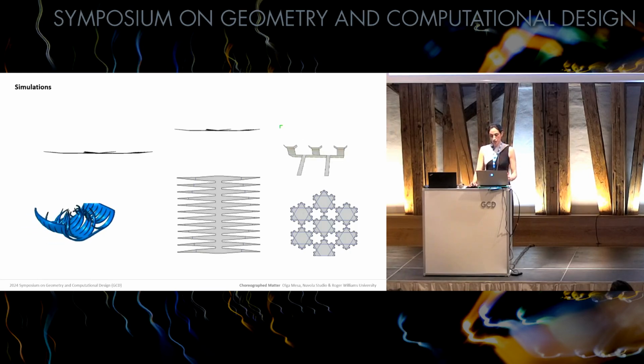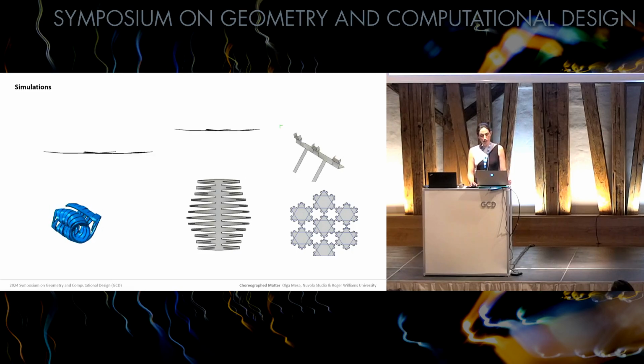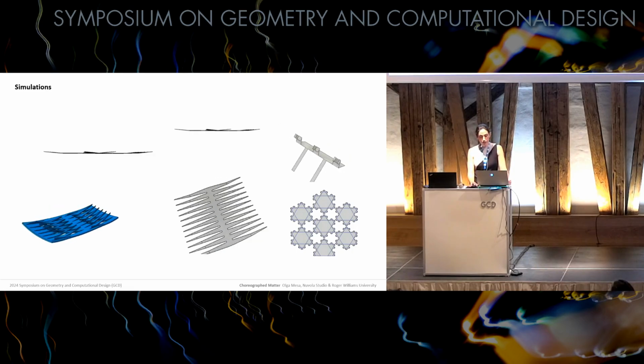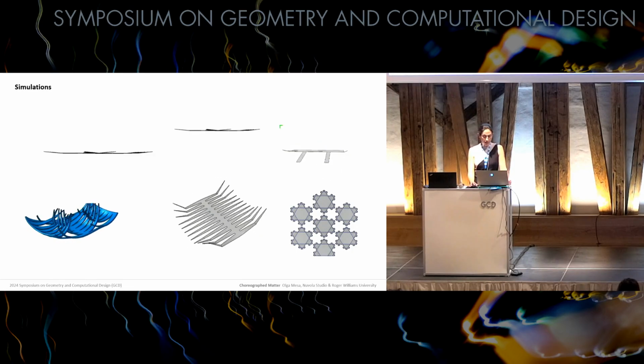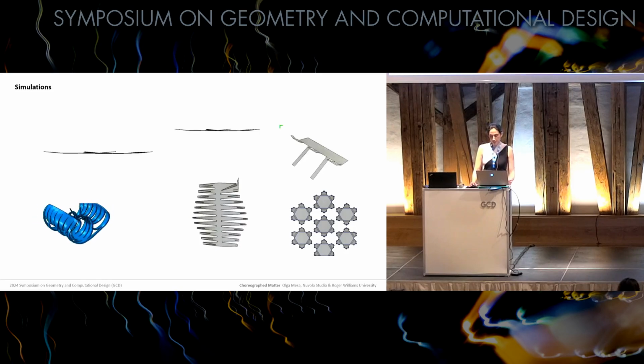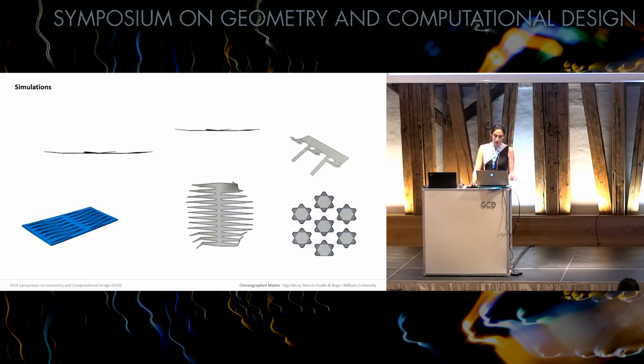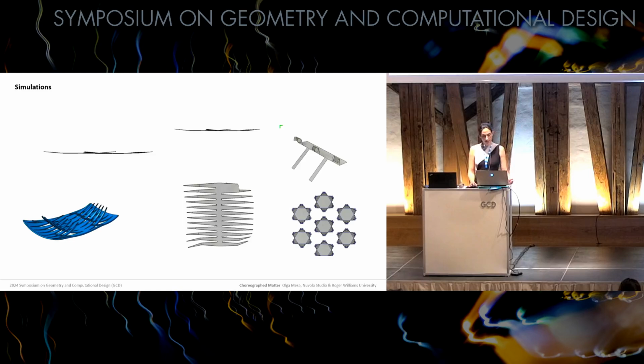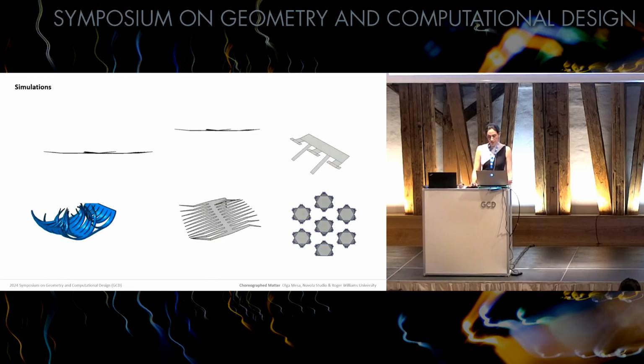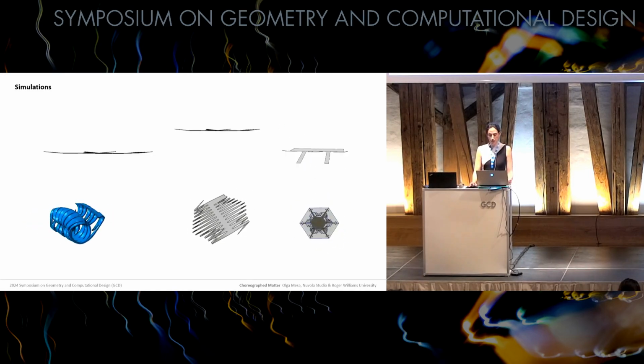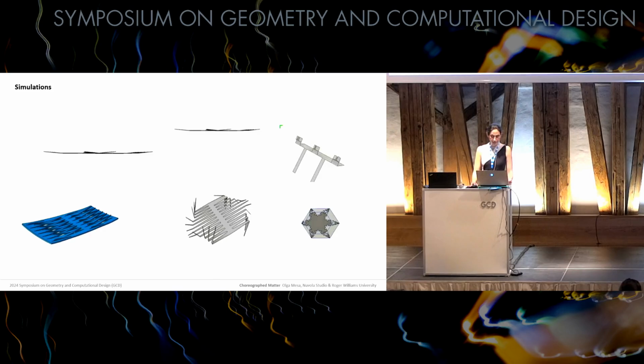To simulate the swelling of the paper, a heat expansion coefficient was assigned to the areas intended not to have the wax. An increase in temperature on those surfaces emulates the swelling of those areas. And this clip shows an increase of 20% to simulate the expansion ratio relative to the absorption rate.